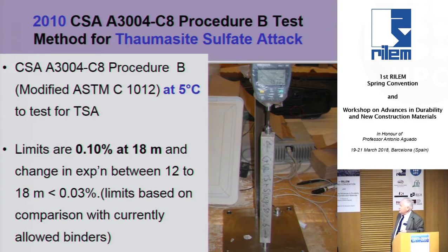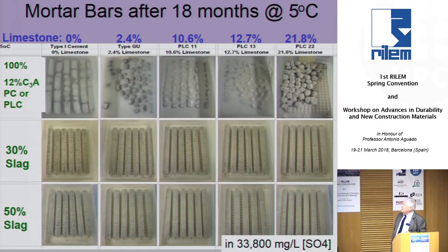And of course, one of the problems with that is that at 20 megapascals, which you typically get within 1 or 2 days, a lot of things like fly ashes haven't done anything. They haven't done any pozzolanic thing in 2 days. Then you put them at 5 degrees C and put them to sleep. And so the problem with that is that it made the pozzolans look very poor in the system. With slag, it wasn't so bad because slag tends to react more quickly, and silica fume as well. So the low temperature doesn't hurt it, but certainly fly ashes were impacted adversely by this cold temperature.